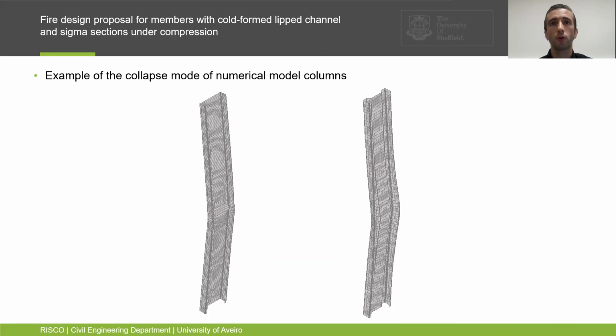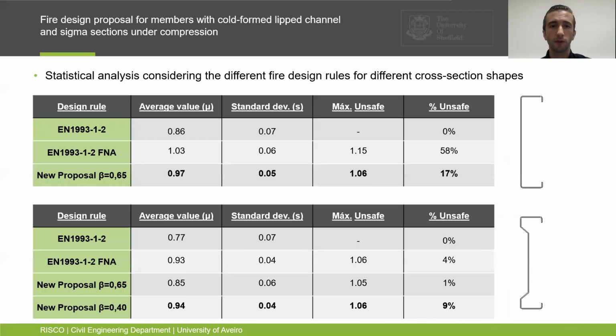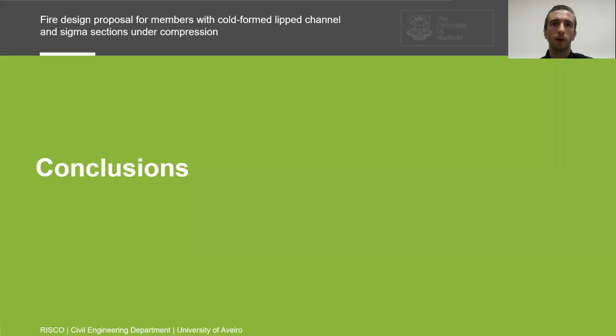Here is presented the failure mode obtained from the tested columns. For a detailed analysis of the obtained numerical results, a statistical evaluation of the methodology is presented. Following the three criteria of the validation procedure proposed by Kruppa, it is possible to observe that the current methodology is too conservative without unsafe results. The French National Annex seems to present a better agreement, however, with significant unsafe results for lipped channel columns. The new proposal presents average values closer to 1 and lower standard deviations, proving to be less conservative and safe at the same time.